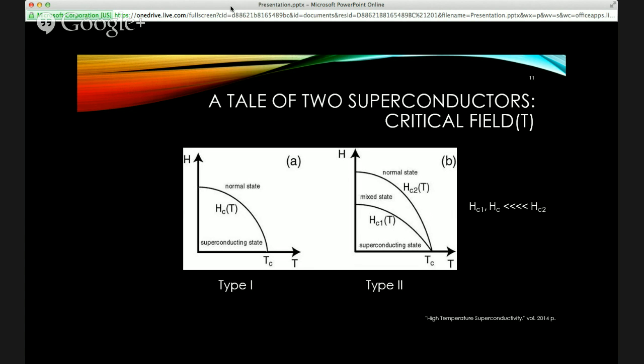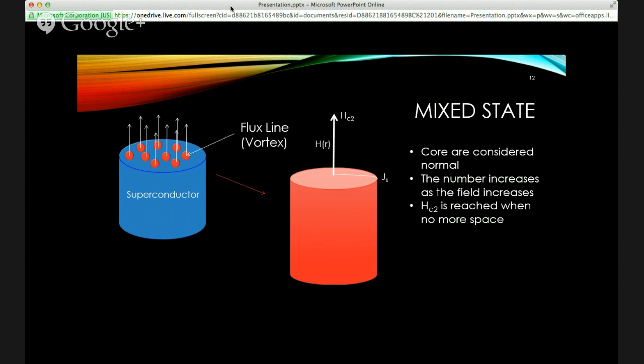And it's worth noting that these images are not to scale, but typically the HC2 is much, much, much, much, much higher than HC1 and HC, which is another reason why type 2 superconductors are more desirable. So I mentioned those flux lines, and this is what actually is happening in this mixed state. So this blue image is a superconductor, and these little red dots would be equal to those magnetic flux lines. So the closer you get to HC2, the more flux lines, the more of these red dots would appear in this superconductor. And it's worth noting that each of these has the amount of magnetic flux as HC2. It just gets to a point where it overpowers and it's not enough room, and then you now have to switch to normal.